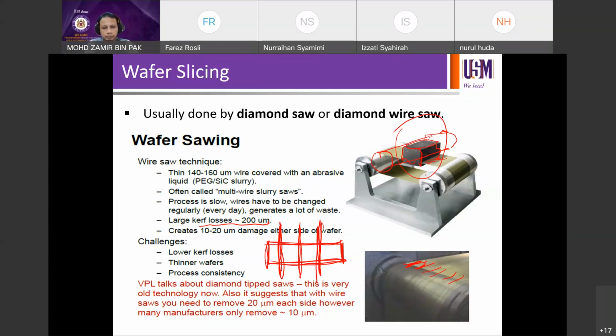So that means the area that you are cutting here, there you akan ada habuk tu kan. So you akan potong. So this will be your wafer thickness, for example, and maybe another one. Maybe this will be your wafer thickness. But in between, you're going to have this kerf loss. Okay, so kerf loss damage on either side. For example, if you use this diamond wire saw, you're gonna lose about say 10 to 20 micron on either side of the wafer. So that means bila you potong wafer yang kat tengah, you might be losing say 20 micron on the left hand side of this wafer.